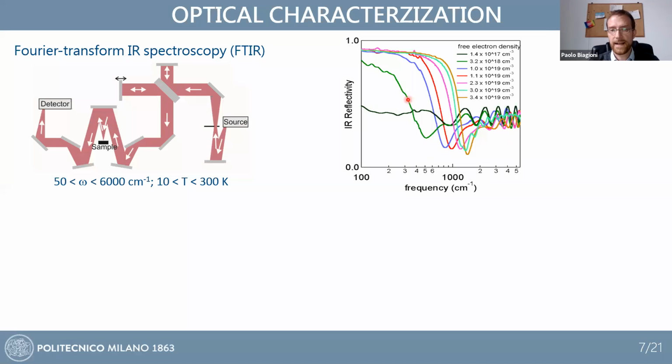All of these spectra are taken for films which possess different doping levels, and you can see the oscillations at high frequencies and the edge due to the plasma behavior. And you can also see that this edge translates towards higher frequencies as the doping is increased, as expected for the basic formula. So in order to extract the dielectric constant from these spectra, we need to model them.